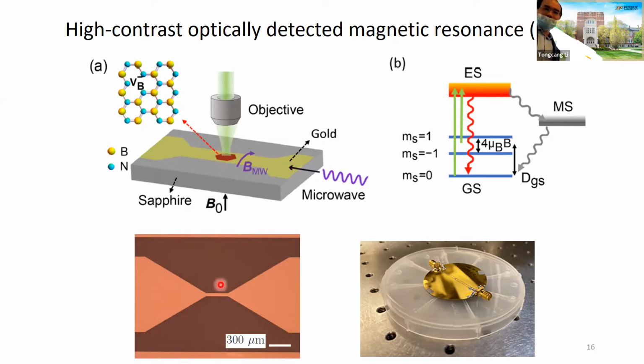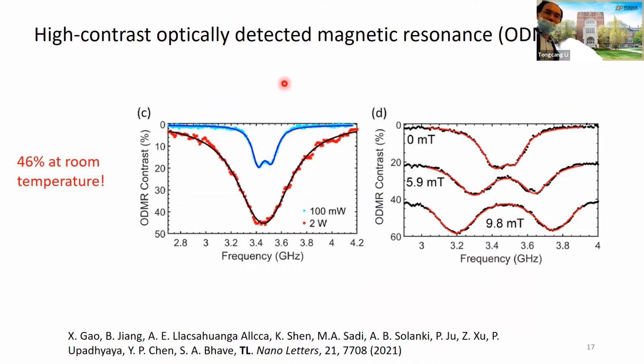With this one, this is the fabricated device. Here is a gold on sapphire wafer, and the hBN will be just tiny at the center. So we have a good waveguide. With that, we also have ODMR contrast as high as 46% at room temperature. Remember the limit is 50%. Even if you drive it completely, let's say 0 is fully bright and 1 is completely dark, by driving them you mix half and half. So the maximum contrast you can get is 50%. So we got 46%. That also means the electron spin is nearly fully polarized, more than 90%.